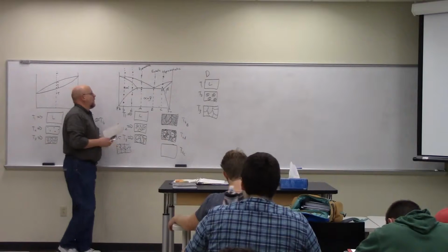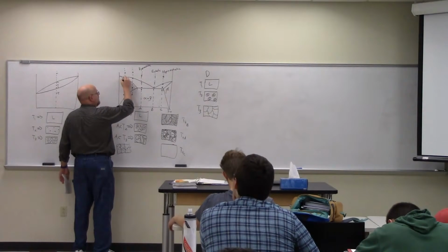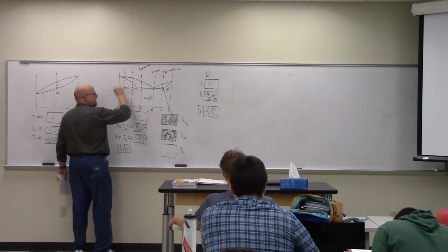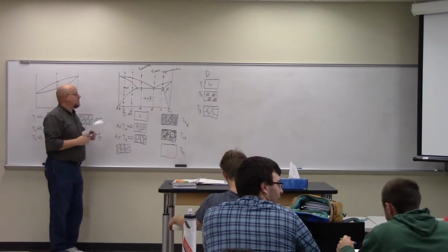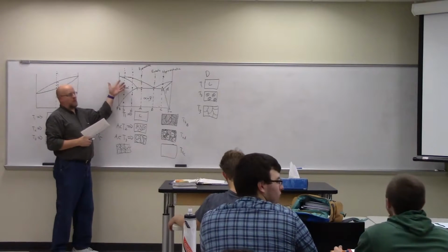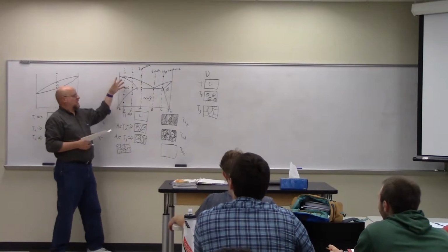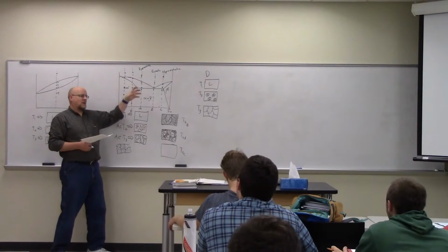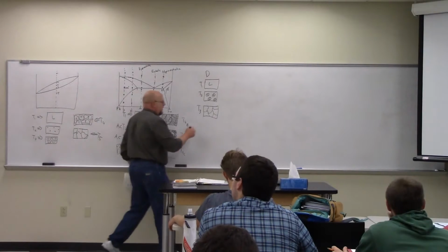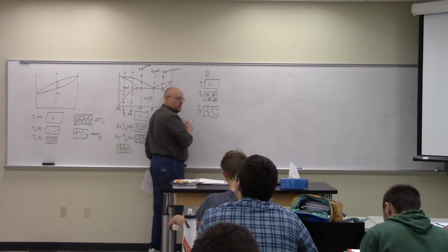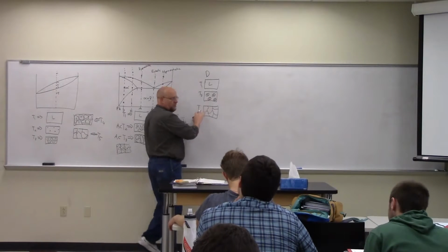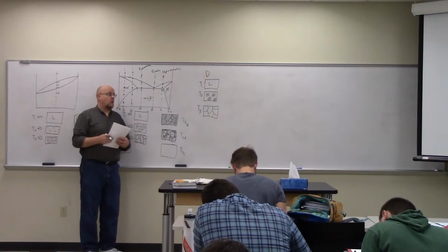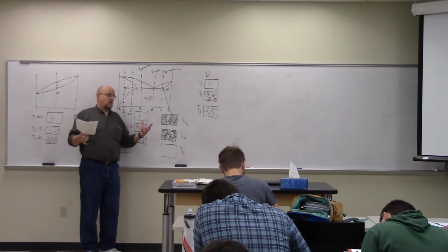No. At this point, the liquid has this concentration, and the solid has that concentration. But once we get down here, the temperature is theoretically still high enough that it redistributes itself. So we don't really talk about having more tin in this part of the alpha and a little less tin there. I wouldn't worry about the variation in concentration of tin in that alpha. That's a level of detail we don't get into because that tin will equilibrate itself.